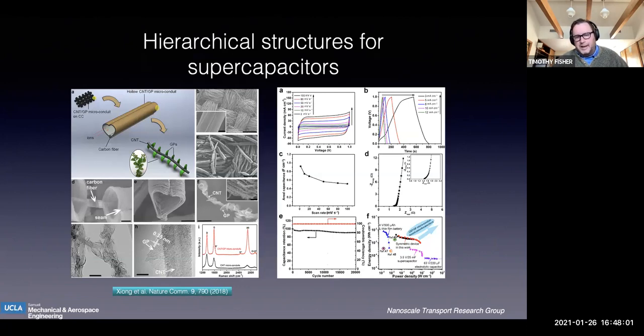We also took that same idea, but instead of having a separate inorganic material, we actually grew those petals. And I'm glad that I can have my pointer here. So this is a petal that's sitting on a carbon nanotube. The reason we did this is we figured out a way to make these carbon nanotube arrays that self-form into a conduit, which is really good if you want to bring liquid electrolyte in. The problem was when we did that with just pure carbon nanotubes growing off of carbon fiber, once we put them in solution, they would just collapse and become carbon nanotube spaghetti. And we needed a way for them to hang together.